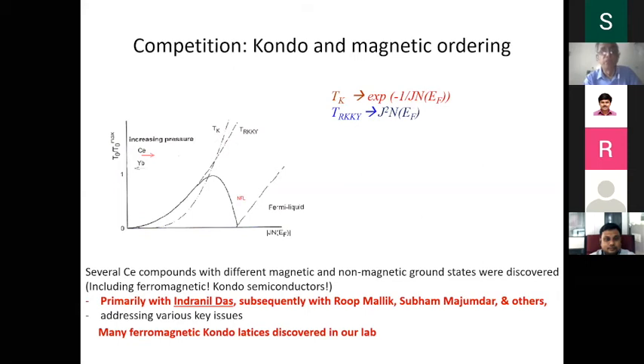One doesn't expect ferromagnetism here, because the Kondo effect tries to kill the antiferromagnetic coupling, and even internal ferromagnetism. Therefore, it was believed that ferromagnetism cannot survive in the presence of the Kondo effect. But we found many ferromagnetic materials which are trying to suppress the Kondo effect. There are many complex variations. We found many materials in that.